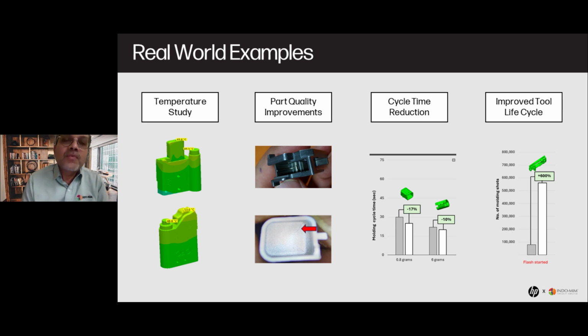Because when we switched over from wrought M2 to maraging steel laser bed fusion, we were very disappointed, because the mold life actually dropped. We were not able to get the required hardness on the laser bed printed tool elements. Now we are able to do M2 material with 63, 66 HRC hardness, so we are hopeful that we will get a very big improvement in the tool life. So we focused on that as well. I'm about to present some of those findings for your reference here.